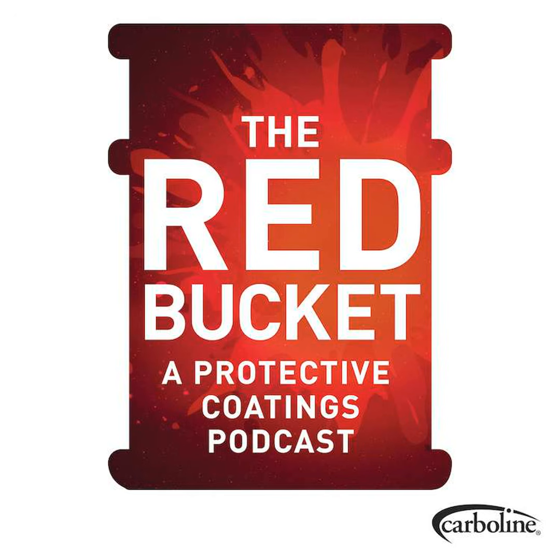So methods of evidence that you might have CUI is using a thermal imaging camera. It's not definitive, but it's going to pretty much tell you you've got moisture in your insulation and you should inspect it. One major oil and gas company, their policy is that every 3 to 5 years, depending on the temperature of the piece of equipment, they will remove 25% of the insulation. If they find corrosion, they basically have to strip it until they don't find corrosion anymore. But most of the time, if you find it at 25%, you're going to find it at 100%. So they have to go through that every 3 to 5 years.